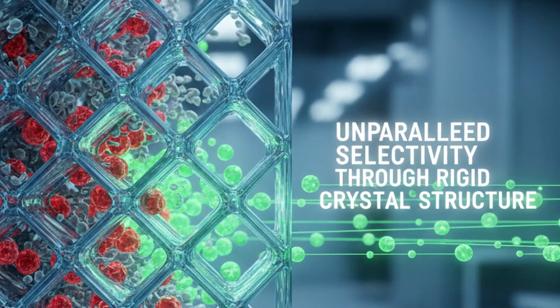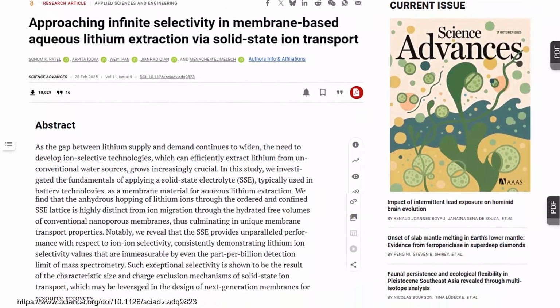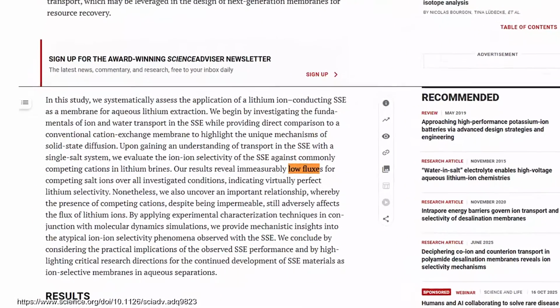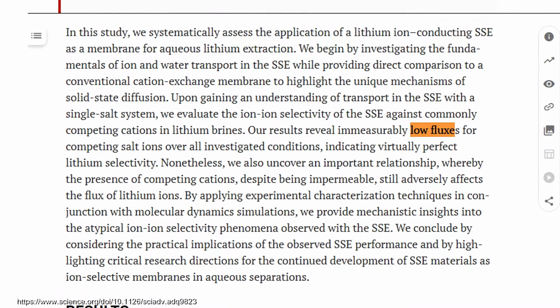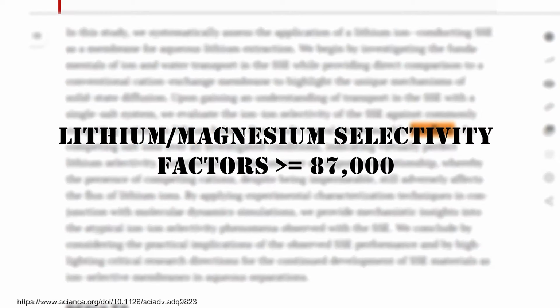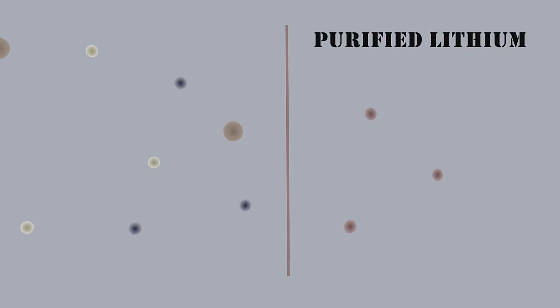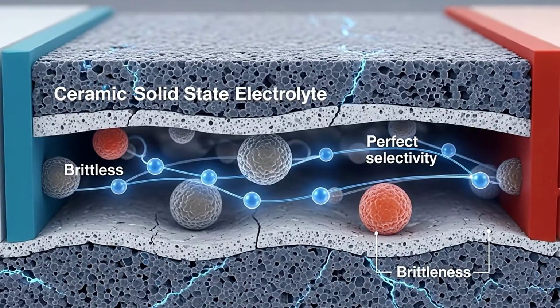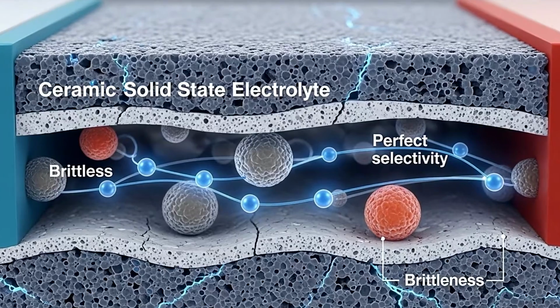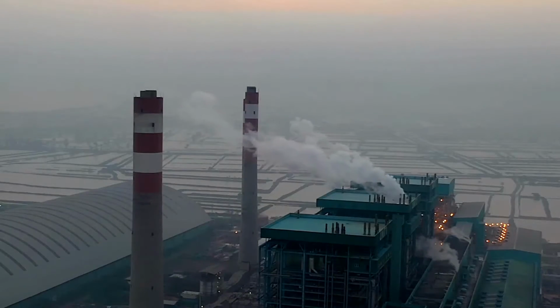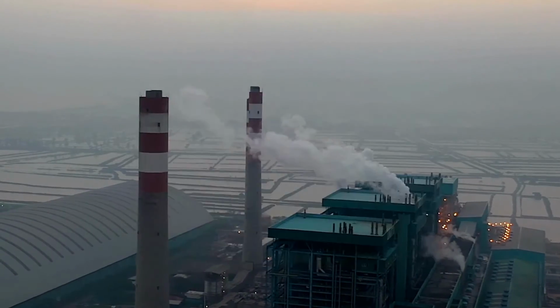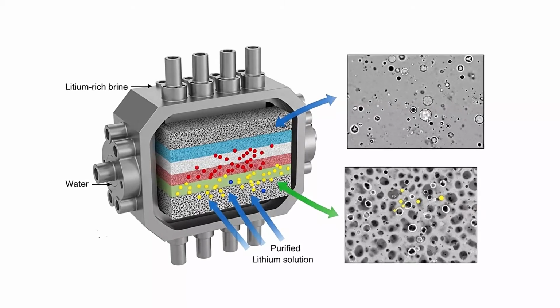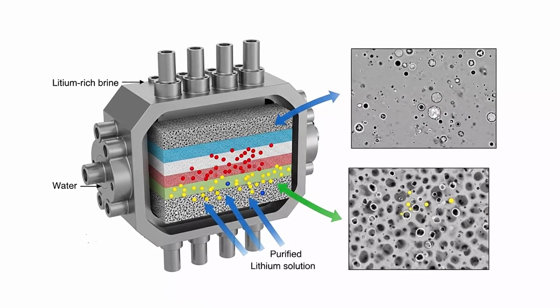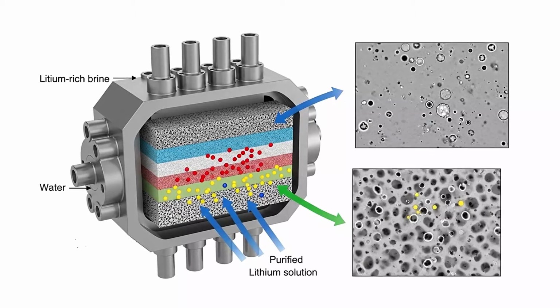The selectivity is unparalleled. Researchers have found immeasurably low fluxes for competing ions, achieving lithium-magnesium selectivity factors up to 87,000 and even higher in some lab tests. That perfect selectivity sounds great, but these ceramic SSE materials are historically brittle. You can't run a chemical plant on a fragile disk. The engineering challenge became, how do we make the perfect filter tough enough for industrial scale?